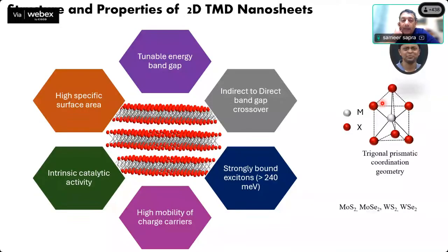That's exactly what happens if you take molybdenum sulfide and you exfoliate it chemically using lithium. Lithium can go within these layers. These are also very good as battery materials because they can intercalate lithium. So when a lithium atom goes inside these materials, it gives off one electron. That one electron is the one that makes it go to the octahedral coordination and also makes the system metallic. Those things have been studied by people, and a lot of research has gone into all that.